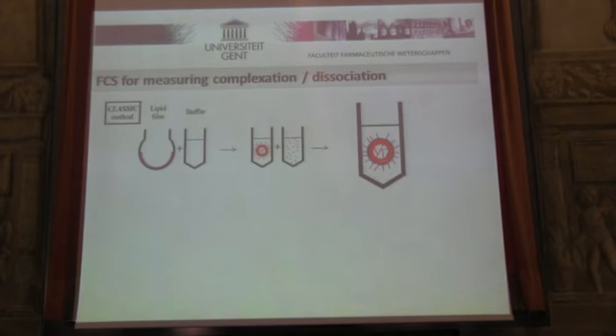And now we use this method to compare two formulations of lipoplexes, two different preparation methods. This is what we call the classic method. I think this is what is usually being done. So you have a lipid film, you hydrate it with a buffer solution, you form the liposomes, and then this is added to siRNA. And our hypothesis is that in such a system, you are complexing siRNA, but where does it go? Probably it's just sitting on the outside. It's attached, but not really protected.